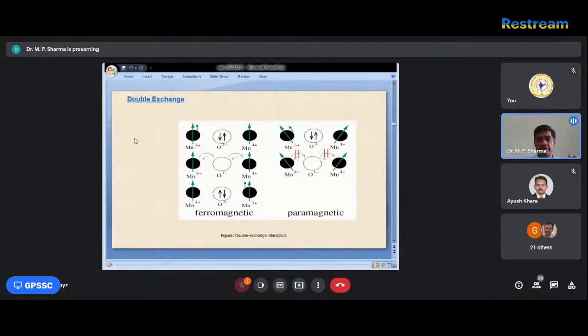Double exchange is described by Zener, which is the electron hopping between Mn3+ and Mn4+. In the case of Mn3+ there are two spins, and in Mn4+ there is a single spin. But when hopping, meaning transferring the spins from Mn3+ to Mn4+, it again gives an up direction. That is called ferromagnetism. This concept was introduced by Zener, and it is defined as double exchange. So it transfers electrons from Mn3+ to Mn4+, and Mn4+ to Mn3+.